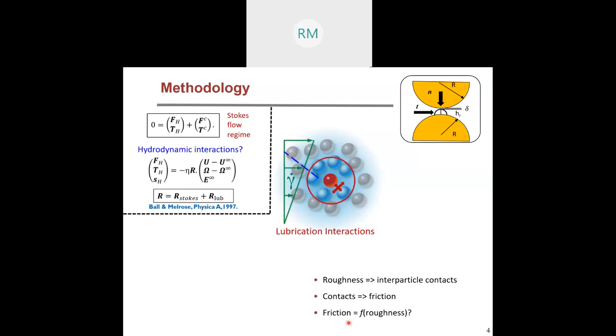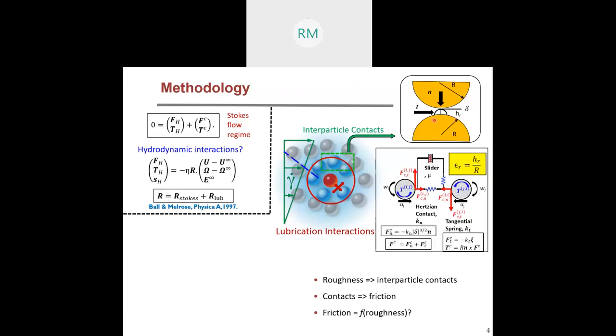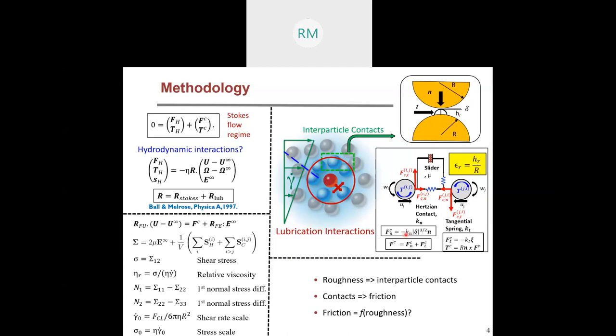To answer why increasing roughness increases the suspension viscosity, we model the hydrodynamic interactions using the Ball and Melrose approximation and model the roughness as a hemispherical bump on the particle surface. We split the contact forces into a normal force and a tangential force, and we also incorporate friction. By calculating the stress in the system we can measure rheological properties such as shear stress, relative viscosity, and normal stress differences.